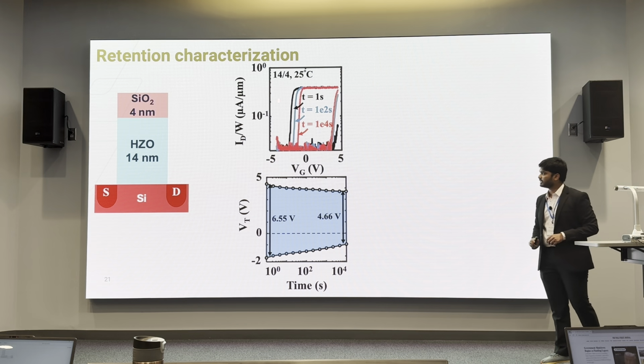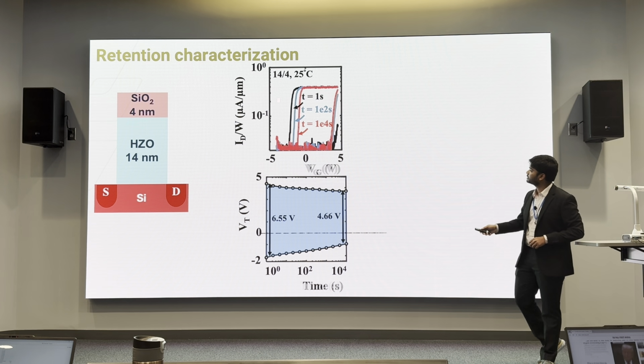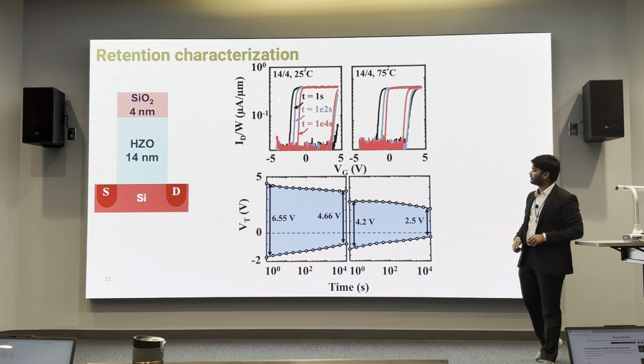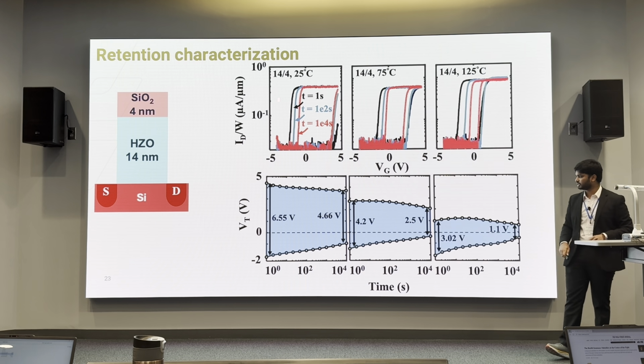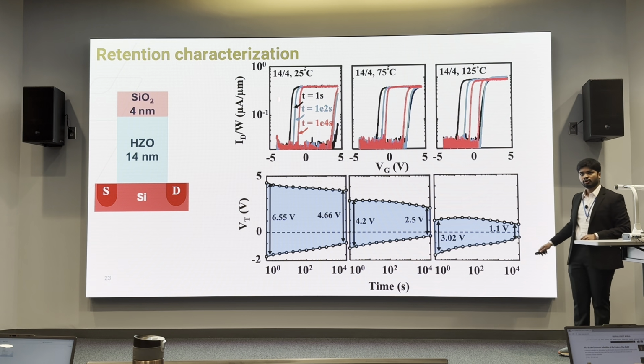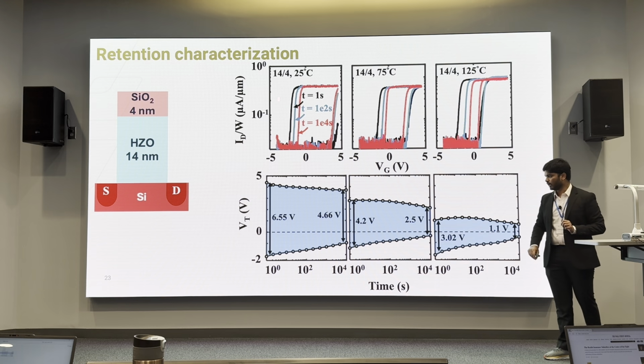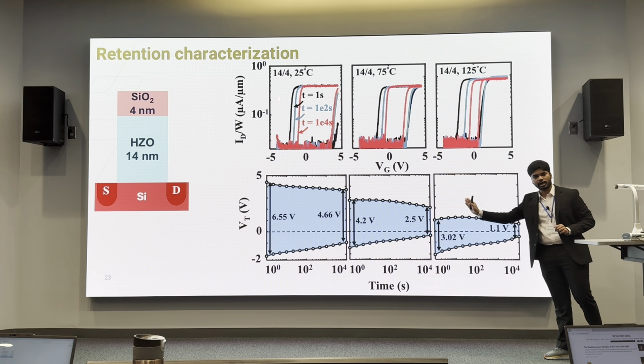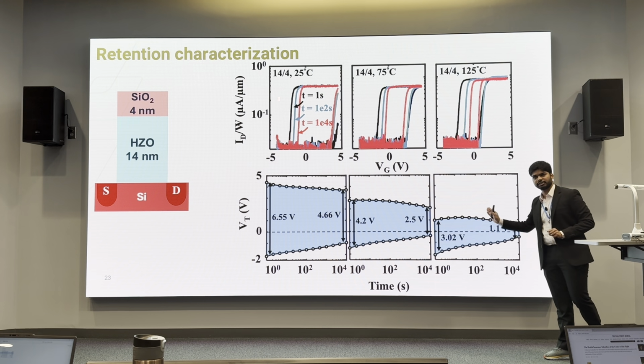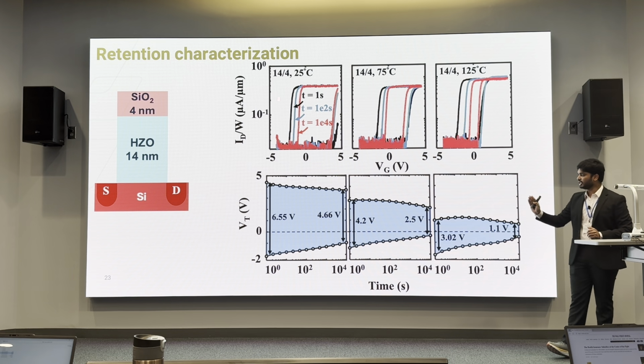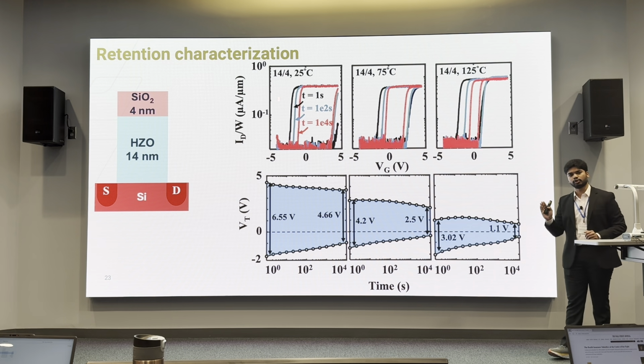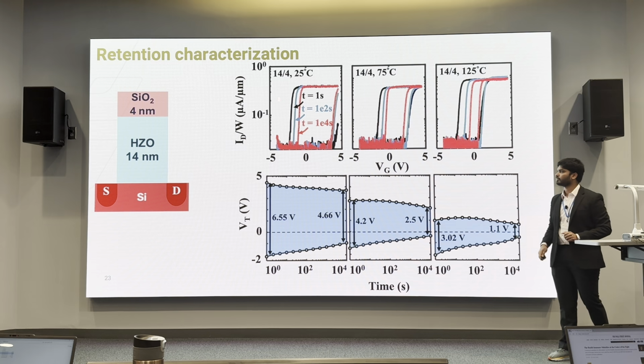Now that I've shown you an example, I'll quickly run through different temperatures. At 75 degrees Celsius and 125 degrees Celsius, we see similar trends. We see 2 things here. One is that the initial memory window at different temperatures continues decreasing, and the second thing is at each temperature, we see a 1.5 to 2 volt decrease in memory window.